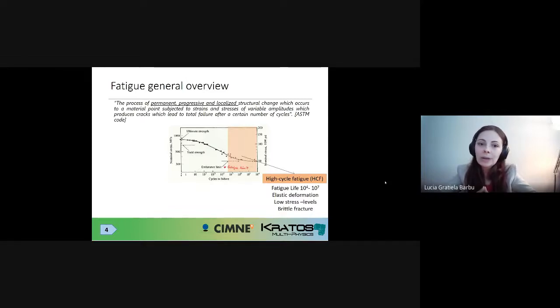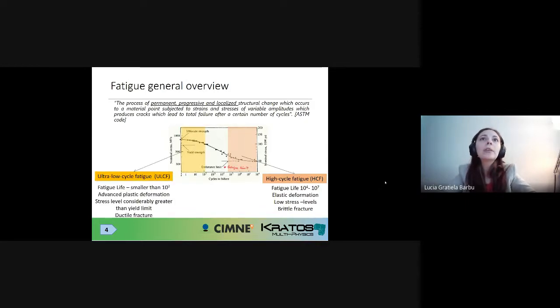In the 1960s, when fatigue became an issue worldwide, this is what was conventionally associated with fatigue, this concept of high cycle fatigue. Okay? Now, later on, another type of fatigue was developed or understood in the literature, which is ultra-low cycle fatigue, the other end of the spectrum. Here we have quite low fatigue lives, in the order of dozens of cycles, maybe hundreds of cycles. We are dealing with a behavior which is completely different from high cycle fatigue. We have advanced plastic deformation, the stress level is considerably greater than the yield limit, and the fracture in this case is very ductile.